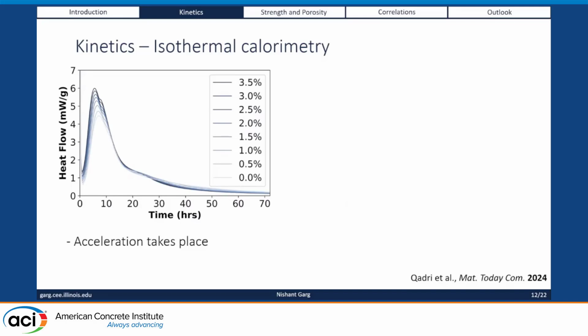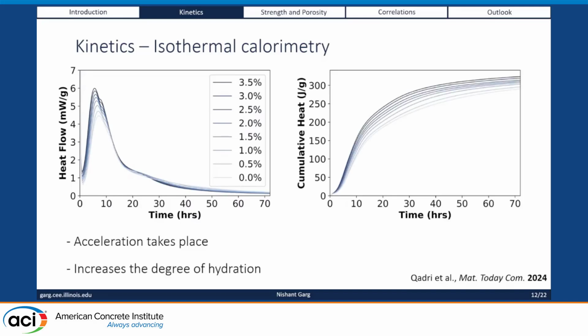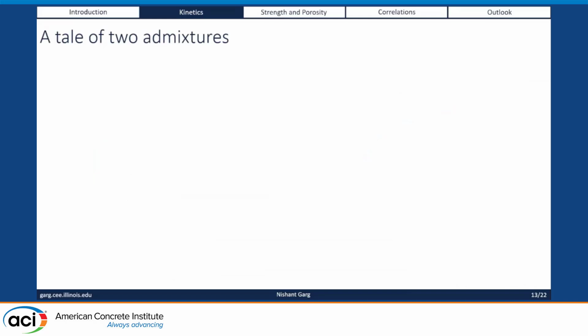If you look at the kinetics from the isothermal calorimetry, again, very standard results. This has been reported in literature several times. Depending on the dosage, there's almost a direct correlation between the dosage and the acceleration that takes place. The cumulative heat also increases on the order of 15 to 20%, which means the overall hydration is enhanced.